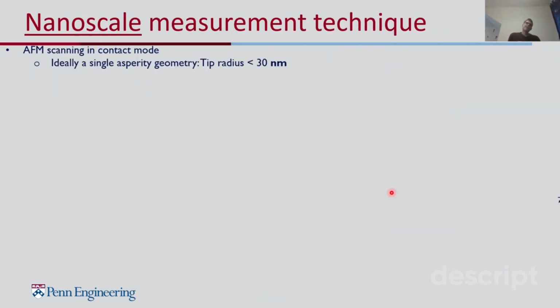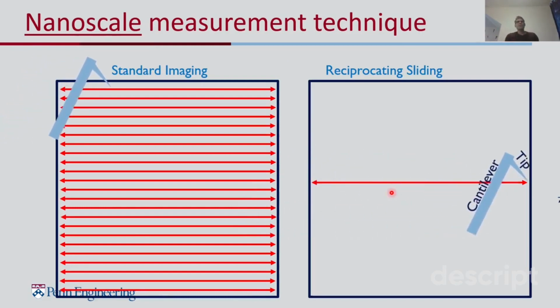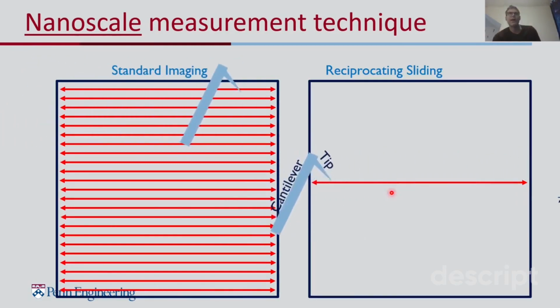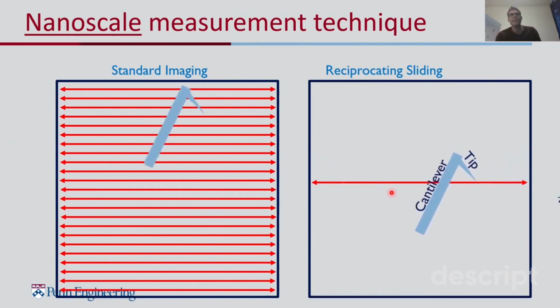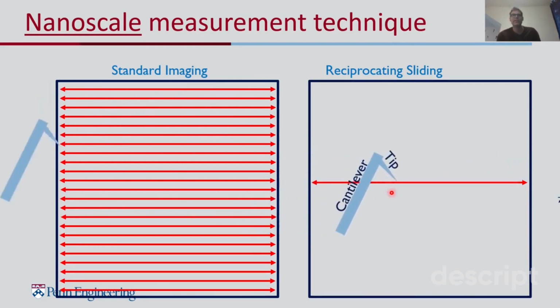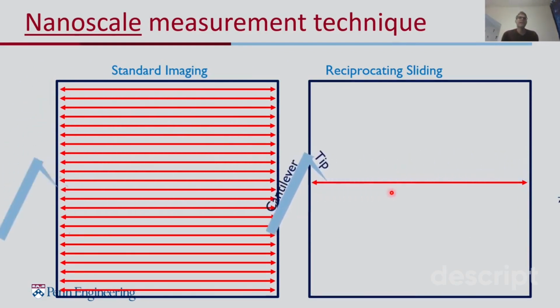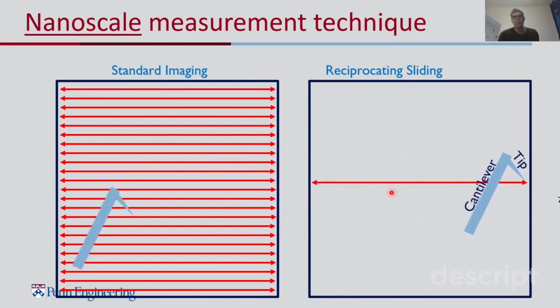Moving down to our smallest length scale now, I'll talk about nanoscale experiments. And these were done with a sharp AFM probe sliding in contact mode on the sample surface. And ideally, the tip is shaped like a single asperity, so with a tip radius below 30 nanometers or so. And I actually made two sorts of measurements that I'll show momentarily. The first one is what I'll refer to as standard imaging. So every scan line, the tip moves such that it's sliding on fresh material. So any friction response that we see here is the inherent friction response for the unworn material.